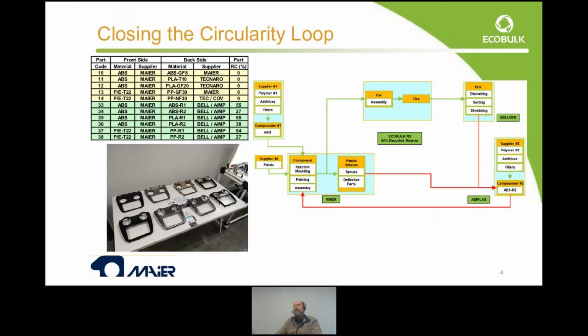The parts were shredded to get some small pieces, chips of less than a few centimeters in size, and those chips were sent to AIMPLAS to use as a raw material to produce new pellets. We reformulated the materials to get two kinds of thermoplastic compounds from recycled materials, to keep under control both the origin and the amount of recycled material we use.